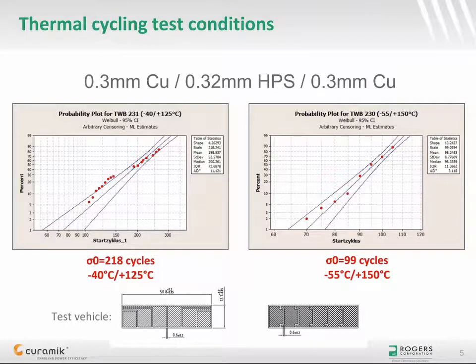C. The characteristic life is cut in half when the temperature span goes from minus 55 degrees C up to plus 150 degrees C. This clearly shows that the chosen min and max temperatures and overall the test conditions largely influence the test results, and you should pay attention to that when specifying a lifetime for substrates.